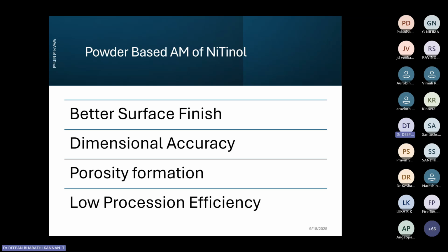The challenge reported in the literature is that porosity is one of the major problems with respect to powder bed based processes, and process efficiency is on the lower side. But the advantage with respect to powder bed fusion is that it has a very good surface finish, and also it has very good dimensional accuracy. So this is another advantageous side.